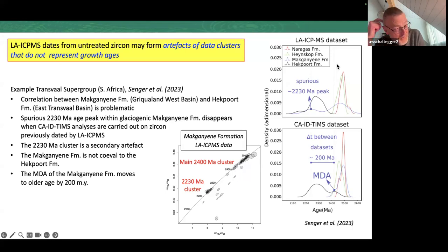Of course, there's a problem of how much your 207 peak is above the baseline of your mass spec. But then I would say in laser ablation dating, when you don't use a multi-collector ICPMS, you have the problem of common lead. So you cannot correct for the common lead because you cannot measure 204. And so the zircon analyses which have a certain component of common lead are usually trending towards the right from the Concordia. So you just kick them out with your